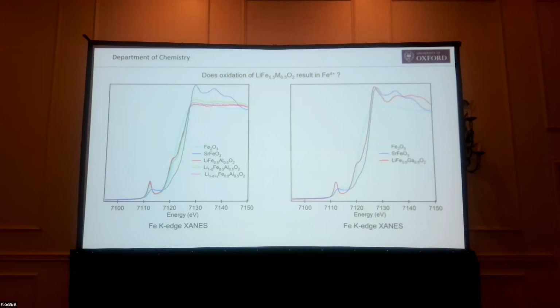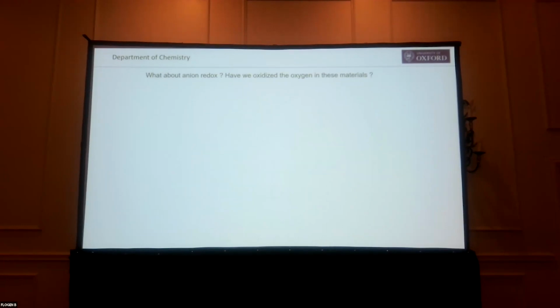In the gallium case, it's the same sort of situation. With the oxidation, it's a bit hard. We lose this feature here, but the oxidation really doesn't do very much. So it's really not clear we've got iron 4. So the question is, do we have oxidized oxygen? Do we have anion oxygen? Because we know we've taken electrons out.